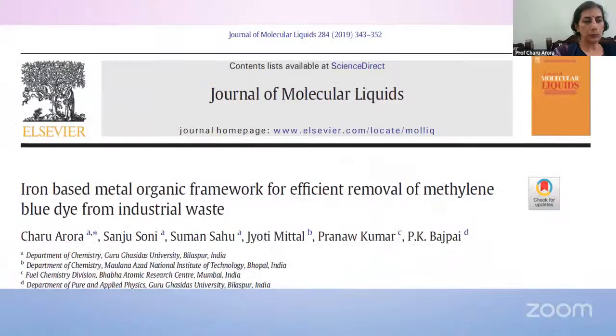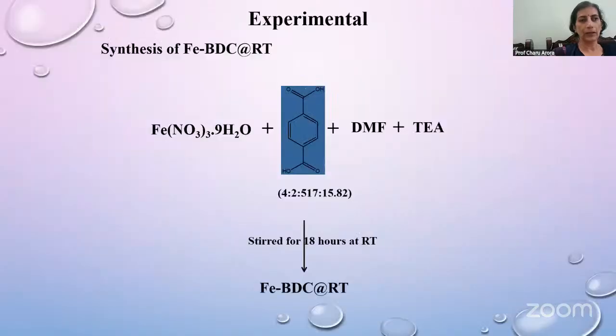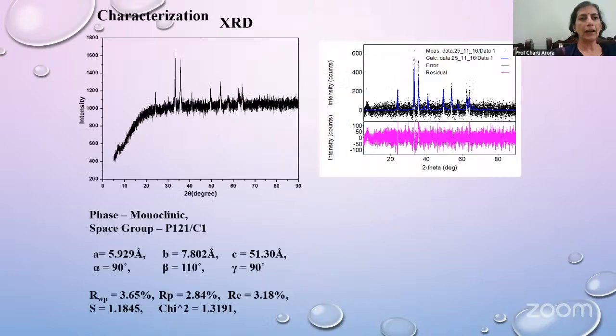Another work I'm going to share is on using a metal organic framework for removal of methylene blue dye from industrial waste. Here the iron BDC MOF was prepared at room temperature using the solvothermal method. A very simple scheme is shown in this slide. It was characterized using XRD and was found to be monoclinic with the space group P121/c1.